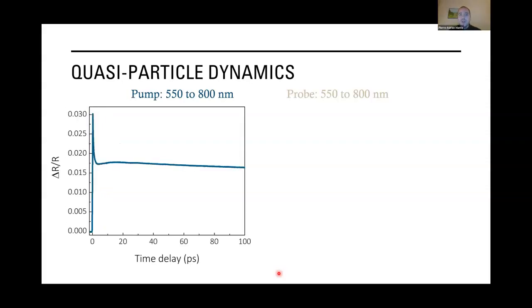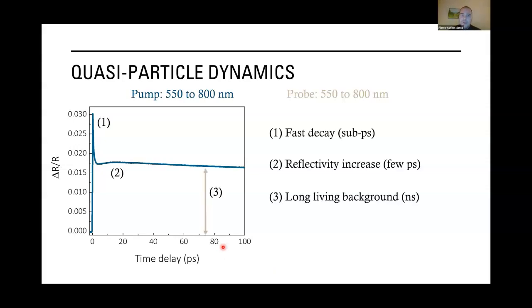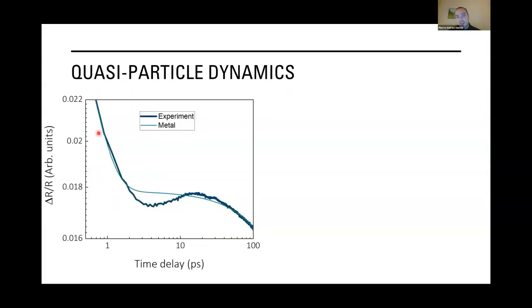But if we look at the larger time scale, we see some discrepancy with this model. We still see this fast decay on the early time scale, but consistently, no matter what our pump or probe wavelengths are, we see a rise on a few picosecond time scale. And finally, on longer time scales, we see this long-living background. We were wondering how to explain this, because a two-temperature model will not be able to explain a reflectivity rise for a wide range of wavelengths. Here, for example, we tried to model with a classical two-temperature model of a metal from a few femtoseconds to 100 picoseconds, and we are not able to reproduce our data.